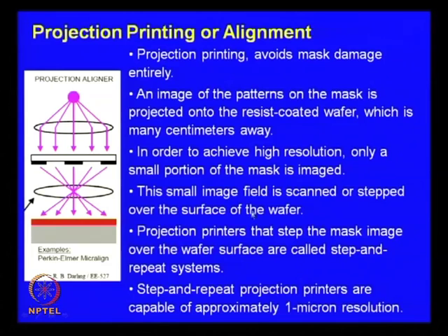I am just coming to it. Projection printers that step the mask image over the wafer surface are called step and repeat systems, again something I will talk about. So, essentially the idea is very simple: you keep the mask substantially away from your film, and in the simplest form you have a lens in between, so that it acts as a condenser and creates an image on the film surface. But in order to have a high resolution, only a small portion of the mask is imaged.